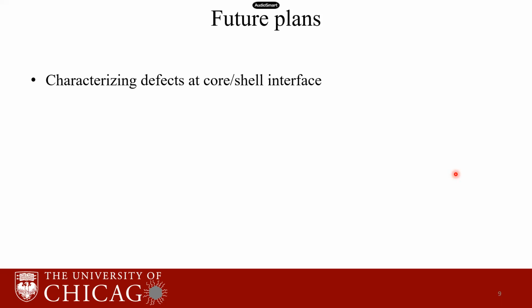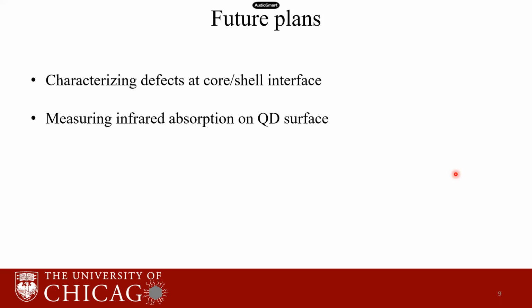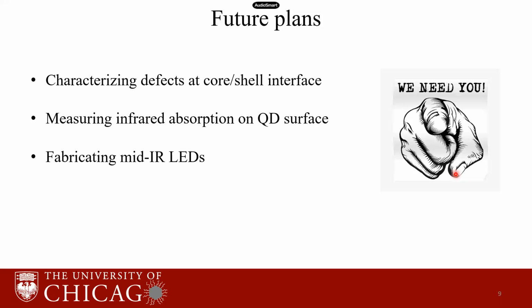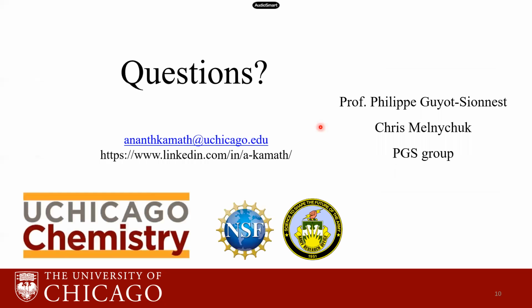We are looking for a method to characterize these defects at the interface. We're looking for a method to directly measure the absorption of the ligands on the surface of the quantum dots, so we can prove that ligand FRET is indeed the dominant mechanism. And we are planning to fabricate mid-infrared LEDs using these quantum dots. So if you have any ideas or you have expertise in instrumentation which can address these questions, please contact me and I would be happy to chat with you.